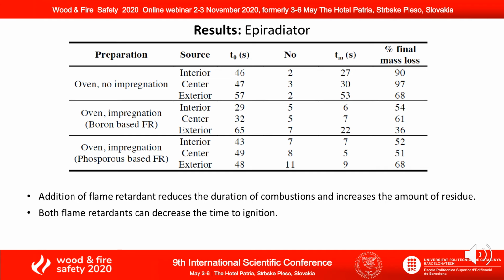With regard to the presence of flame retardant, we can observe that in both cases, boron and phosphorus-based flame retardants reduce the duration of combustion and increase the amount of residue. But they can decrease the time at which the first ignition appears due to a lower thermal stability of the flame retardant samples.